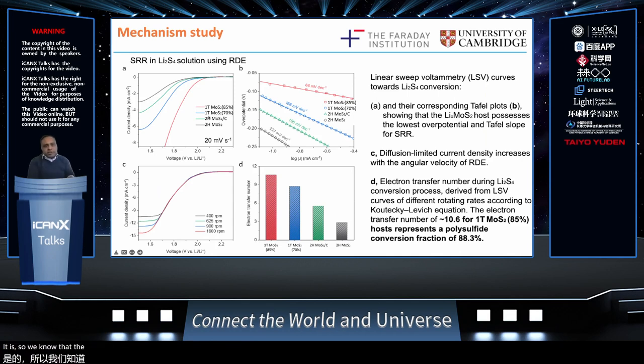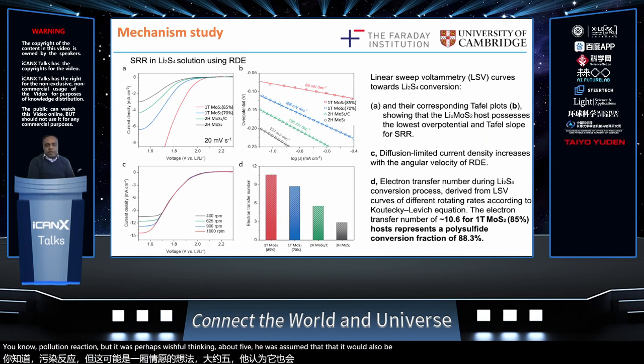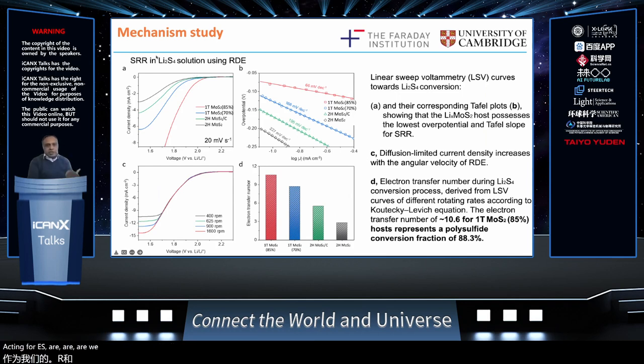So we know that the 1T MoS2 is catalytically active. I showed you results for the hydrogen evolution reaction, but it was perhaps wishful thinking on our part to assume that it would also be catalytically active for the sulfur reduction reaction. So to check first whether it's active for SRR, we measured the sulfur reduction reaction in polysulfide solution. Those results are shown here, where again, this is a very similar measurement to the HER measurement in the sense that we have a three electrode geometry, but we have a rotating disk electrode here.